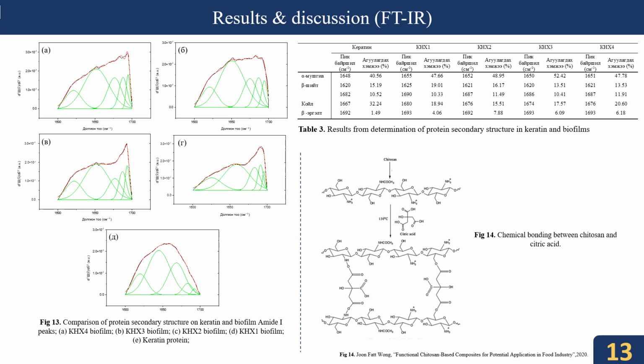Okay. When interacting with other biological polymers and proteins, citric acid not only creates hydrogen bonds but also changes the macromolecular structure of the proteins. Therefore, calculations were made to determine the secondary structure of proteins on the amide 1 peak of keratin and citric acid-based biofilms. The proportion of protein secondary structures such as alpha helix, beta sheet, coil, and beta turn is determined by calculating the value from 1,700 to 1,600 of the infrared spectrometer absorption results using the Gaussian distribution.